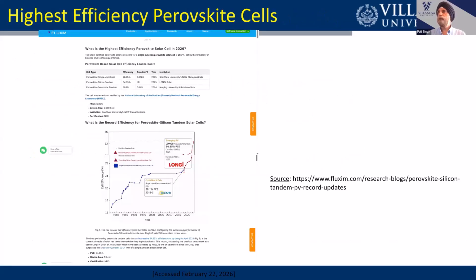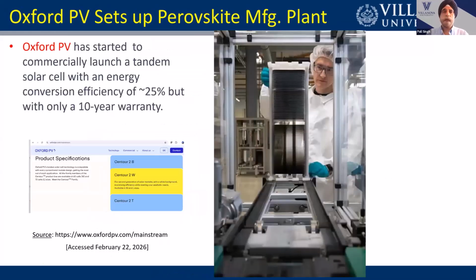The highest efficiency perovskite cells, as you can see in this slide, is up to 34.85% reported by Longi Solar. And again, this is a perovskite silicon tandem cell. Now, in terms of commercialization, the company Oxford PV has started to commercially launch a tandem solar cell with an energy conversion efficiency reported to be of the order of 25%.